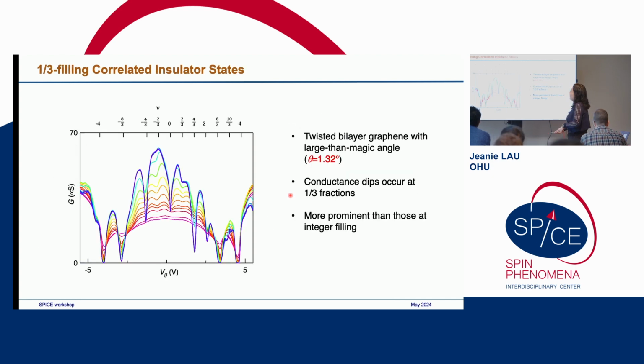Now, those are magic angles. We actually have some large angle devices. And if you ask me why we do large angle, that's just because we obtained large angle. I said, oh, what the heck, let's measure it. But it turns out we see interesting stuff. This is an angle of 1.32 degrees. This is conductance in microsiemens as a function of gate voltage, and the top axis plots again the filling factors.